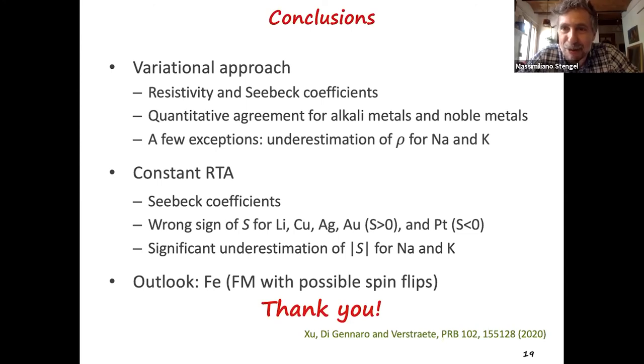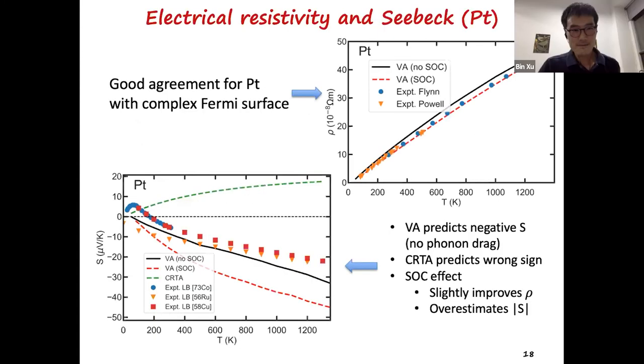Then Aldo Romero, how are the resistivity values affected by the exchange and correlation? Here we use the PBE pseudopotentials, I think. But I think some time ago, I also tried different pseudopotentials, in particular for lithium. I think there will be some quantitative difference, but for the sign of the Seebeck and resistivity is pretty robust, I would say. For Seebeck, it's a little bit sensitive. So it really depends. I think because the pseudopotential exchange correlation functional can also change the relaxed lattice parameters. So in that sense, it can also affect the result, I think. Okay.